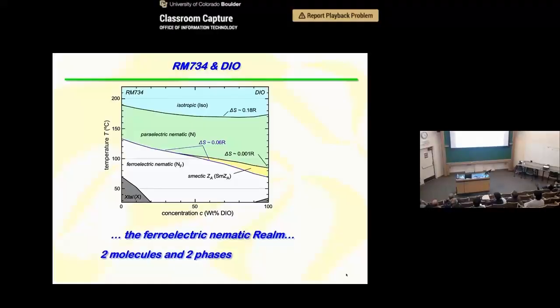Now the interesting thing about this is that this phase boundary is fairly straight. With respect to the thermodynamics of the nematic and the ferroelectric nematic, this behaves like an ideal mixture, which means that in the mixture, with respect to the ferroelectric nematic ordering, an RM734 molecule can't tell whether it's interacting with a DIO or with another RM734. So the molecules are behaving very similarly in this phase.